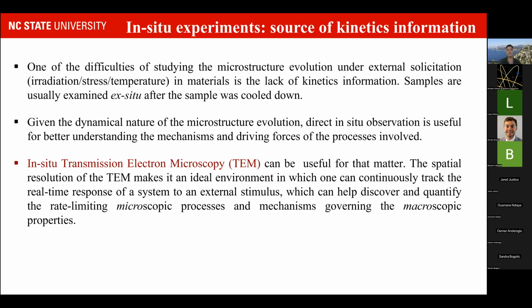One of the difficulties, not the main difficulty, of studying the microstructure evolution under external solicitation, whether it's irradiation, stress or temperature, is the lack of kinetics information, because the samples are usually examined ex situ, especially if it's a material that was subject to spend time in a reactor. We always need to wait until it's out, cool down, safe to manage, and then we can look much later at what the microstructure was. The same thing, in fact, with ion irradiation. If it's not coupled with an in situ investigation technique, you irradiate your sample at a given temperature, but then you have to cool it down and process your lift out in order to probe the microstructure.